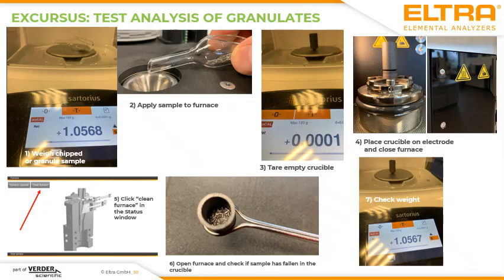And then you weigh back the sample on the balance. When the applied weight of the furnace and the measured weight on the balance is the same, you can be on the safe side that all of the granule samples will fall directly into the crucible. This can sometimes be a little bit tricky when you have drilled samples or an unusual sample shape, because then you may have blocking in the furnace. When you have blocking in the furnace after this test, it's easier to clean the furnace with just a brush, because you have not performed an analysis which may cause sticking on the upper electrode.